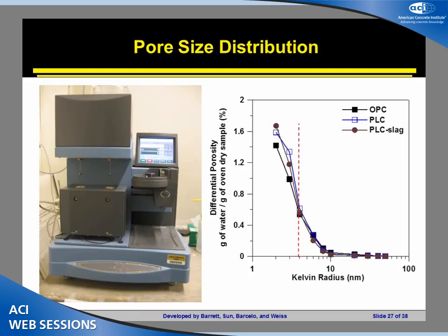Now, the proof is really in the pudding, in what size pores you get back out of the system. And what we've done here is we've done a test where essentially we've dried out different pastes, and by drying them at a known humidity, you can determine the relative proportion of pores inside of that humidity range. And if you look at the OPC, the PLC, and the PLC slag here, from the highest humidity way down to about that 60% humidity I was talking about before, that 3 nanometer pore size range, you would say that these curves are virtually identical.